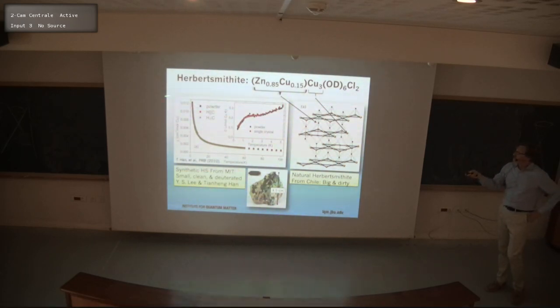There's no bifurcation or peak in the AC susceptibility, and the specific heat does not show a peak. There's no kind of phase transition into an ordered state. So a lot of things that are not there. And the question is, does that imply that there's something there, such as entanglement, spinons, fractionalized quasiparticles, and so on? That's basically where the research is now operating, and I think it's going to keep going for some time.